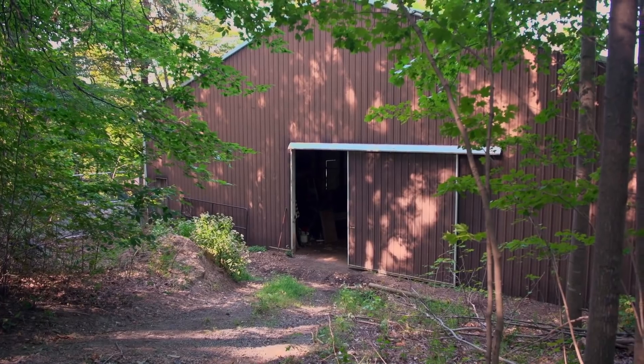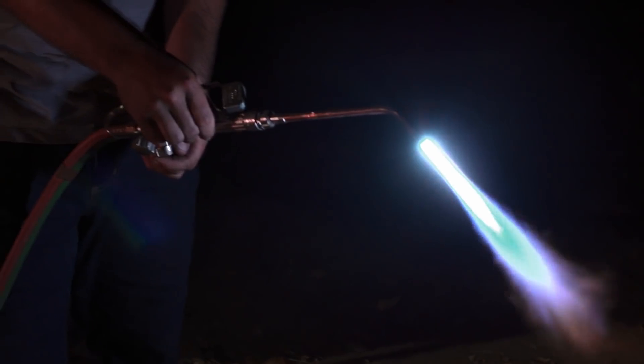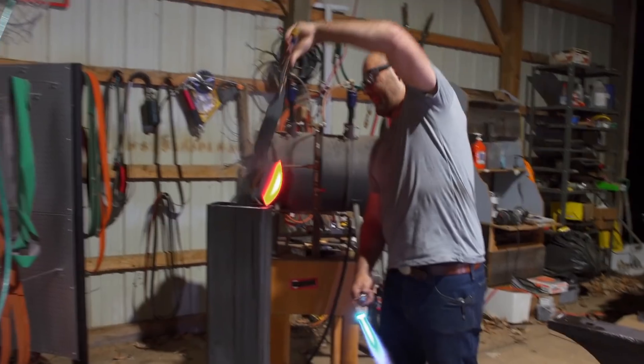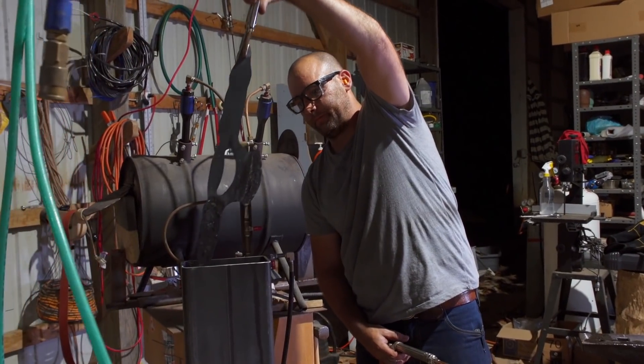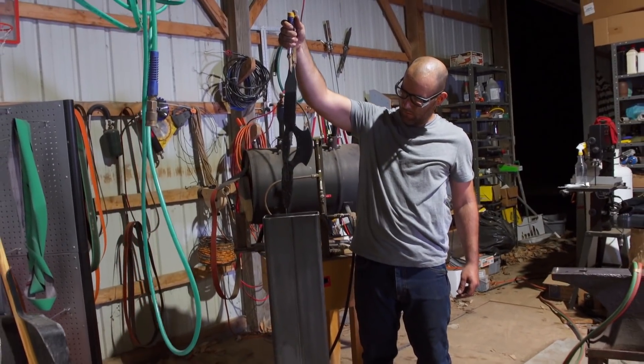Day two, I'm a little tired this morning, but I feel great, ready to get this show on the road. I decide that I'm going to go with a torch heat treatment because the handle doesn't need to be hard — I just need the blades hard and the knuckle blade hard. I'm scared I'm going to crack it in half because right after the quench it is brittle, so any little shock or hit could cause catastrophic cracking. Luckily, I don't see any cracks, so I think the quench went well.